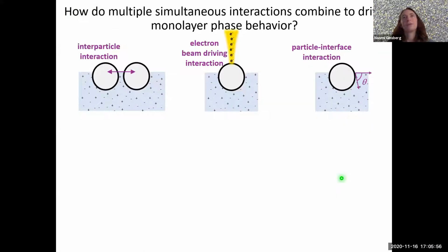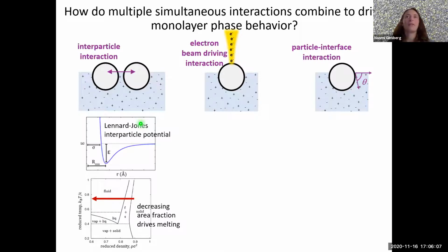Okay, so what have we learned so far? So we focused so far on the interparticle interaction, which we've now captured in a fairly simple model involving this Lennard-Jones potential. And we found that the decreasing area fraction drove the melting transition. So by inference, the electron beam must be implicated in reducing the area fraction. So I'll next explain how, by focusing on these other two interactions in this problem, we can try and build the rest of our model.